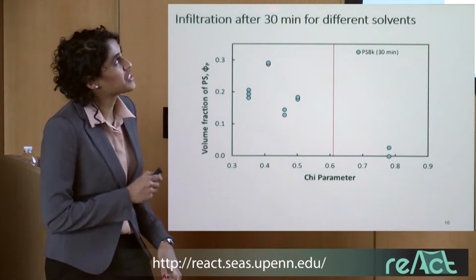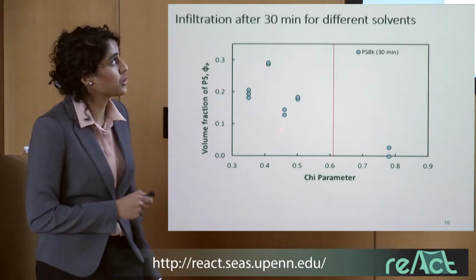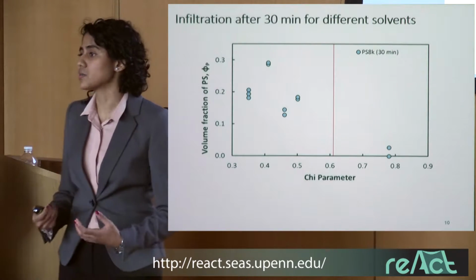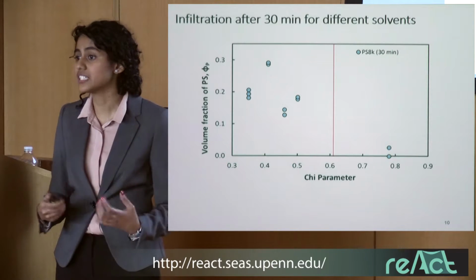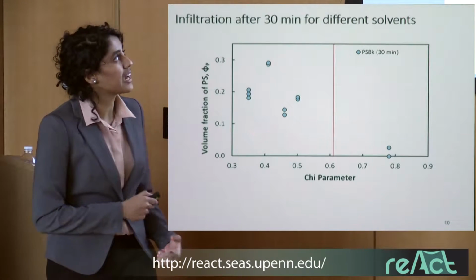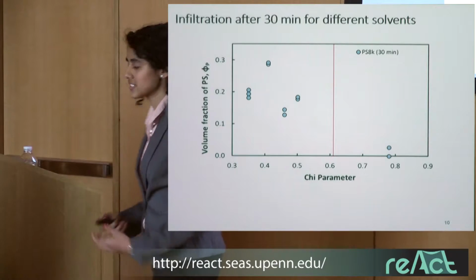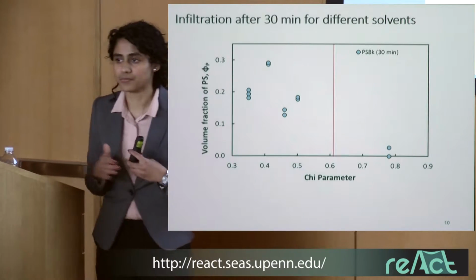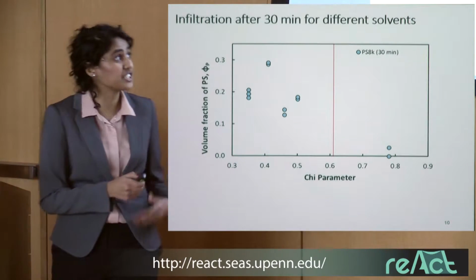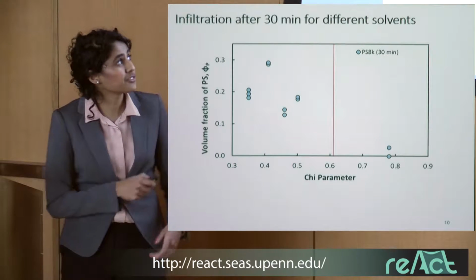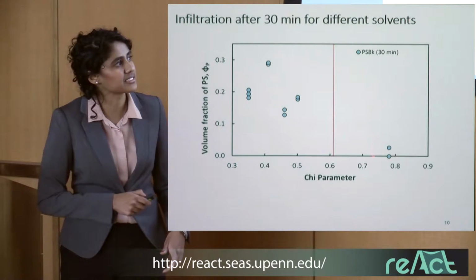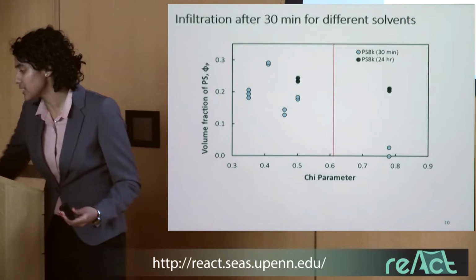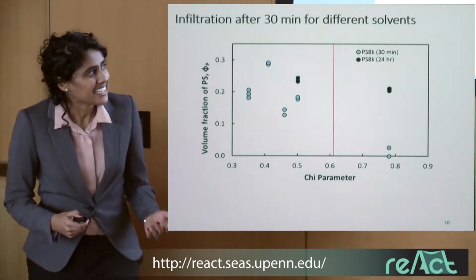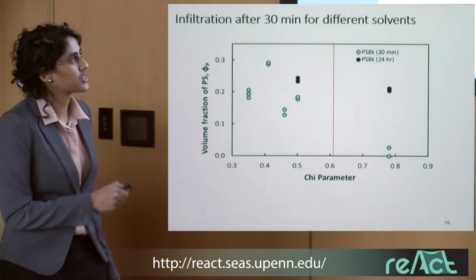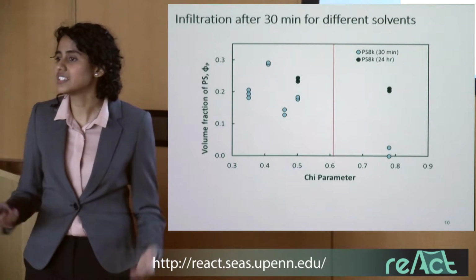Now, the reason why I don't run it for much longer is that, for one, these seem to occur within 5 minutes in the really good solvent systems. However, I also observe some de-wetting. So there's some instability of my films given long enough exposure times in the good solvent regime. However, for my poorer solvents, this 0.5 case and this 0.78 case, I can run it for longer, and I see that unexpectedly, even with the poor solvent case, I get infiltration given enough time.